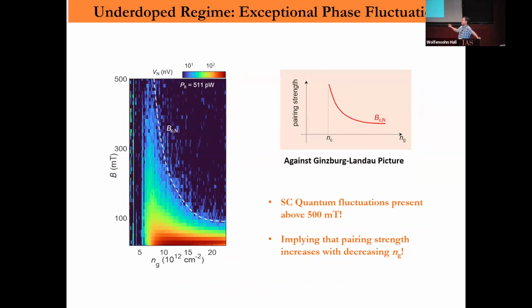So there's something that rapidly increases. This is information not seen in the resistance. So what is this? If you look at this data, what I'm saying is that you're starting from a superconducting state, and then you increase the magnetic field, which means you bring more and more vortex into the system. And this BCN is really when the vortex signal disappears, right? So that's when you have too many vortices, and then all the electrons become normal.